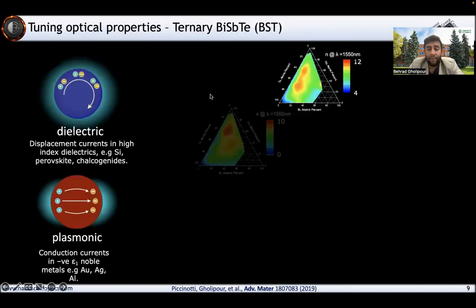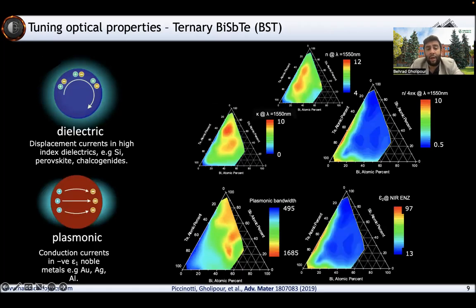So just to give you an overview of what can be done, for example, on the ternary side of things, if we take antimony telluride and add a bit of bismuth in there, bismuth antimony telluride, you can see that we can look at the dielectric properties and the plasmonic properties of the material system. On the dielectric side of things, we define a figure of merit, n over 4 pi k, at 1550 nm because of the telecom band applications of that wavelength. What we would want is a high refractive index and a low loss in telecom applications, and much higher absorption in the visible part for photovoltaic applications.